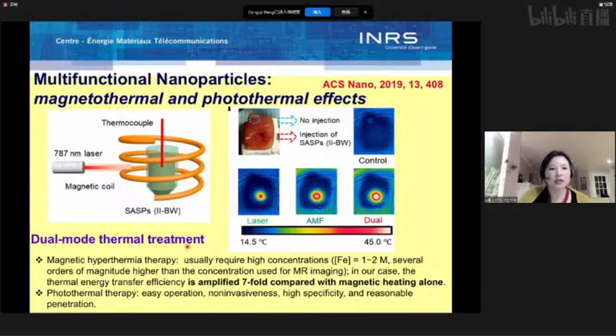effect. The advantage is very interesting because for magnetic hyperthermia therapy, usually it requires a high concentration of iron, several orders of magnitude higher than the concentration used for magnetic resonance imaging. In our case, the thermal energy transfer efficiency is amplified 7-fold compared with magnetic heating alone. Because of that, we can use a lower concentration of iron oxide particles, so as to make them also suitable for magnetic resonance imaging. And also photothermal therapy has its own advantages like easy operation, non-invasiveness, high specificity, and reasonable penetration. So with that, I think I can finish.